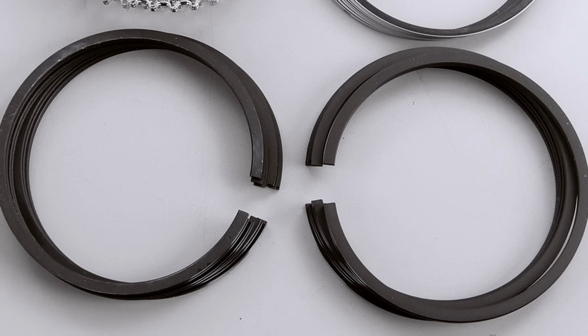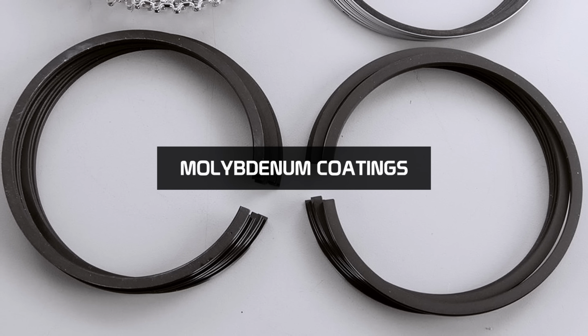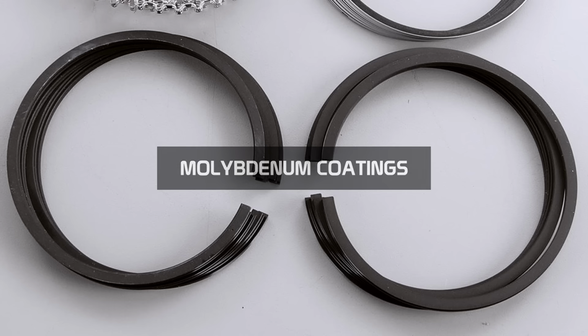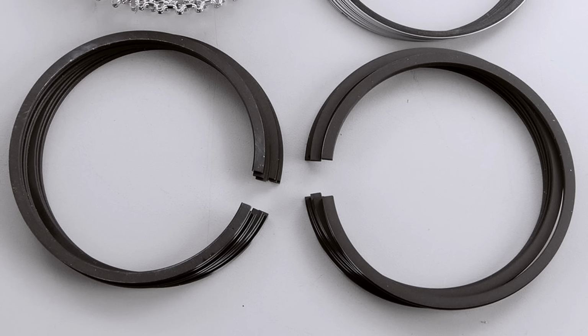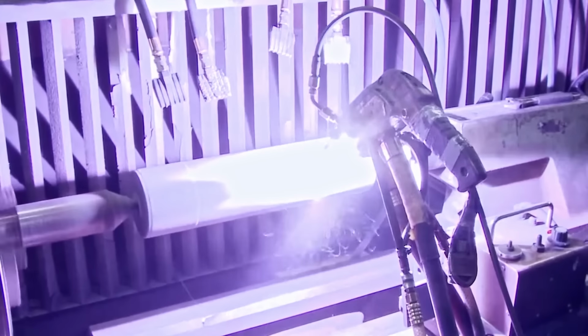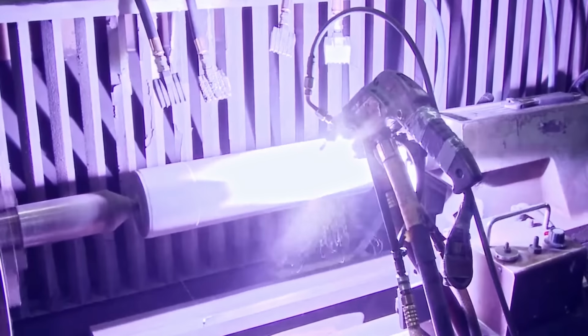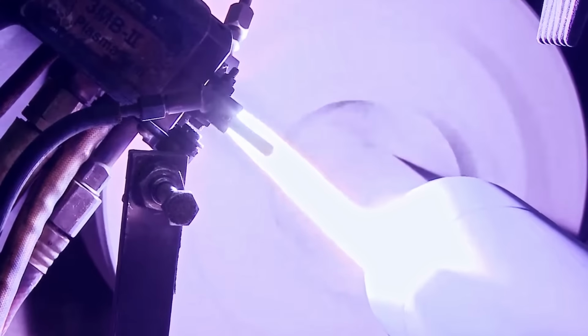The 1960s saw the introduction of molybdenum coatings that offer a balance between the surface properties of cast iron and chrome. Applied via flame or plasma spraying, molybdenum has a high melting point of 2,620 degrees Celsius and offers excellent temperature resistance while being softer than chrome, making it easier to break in. The coating's porous structure allows oil to collect in microcavities, providing lubrication under both extreme and emergency conditions. However, they do suffer from coating detachment in cases of poor installation or extreme cylinder conditions.